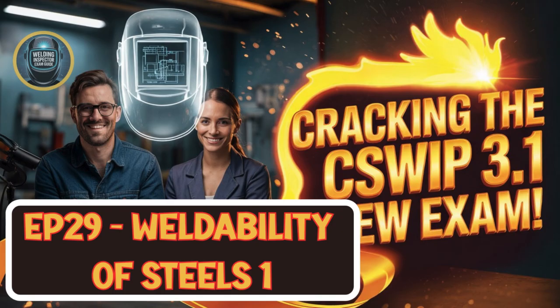What's the core mechanism? Okay, this typically occurs in standard grades of austenitic stainless steel that are not the low-carbon grades. So think regular 304 or 316 as opposed to 304L or 316L. The L stands for low carbon. Got it. Standard grades. When these standard grades are heated during welding, particularly when they spend time in the critical temperature range of around 600 to 850 degrees Celsius, chromium carbides form at the grain boundaries within the HAZ.